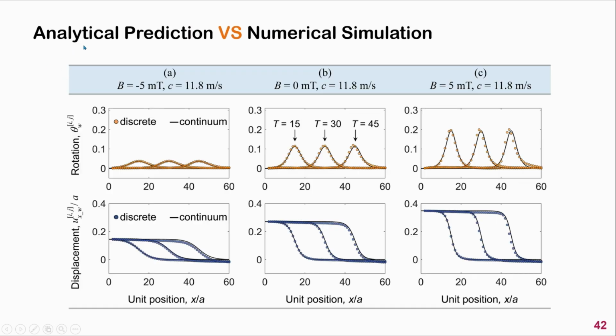The comparison between analytical prediction and numerical simulation is shown here. The upper panel is for the rotational movement, and the bottom panel is for the translational displacement component. In each plot, we present the displacement profile at 3 moments. We can see that in each case, the analytical prediction given by the continuum model matches well with the numerical simulation. More importantly, by changing the direction and the magnitude of the external magnetic field, we can change the amplitude of the solitary wave.